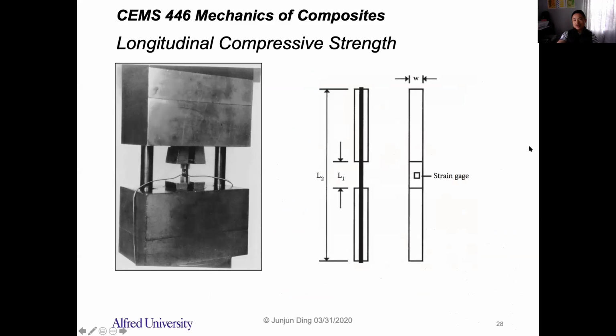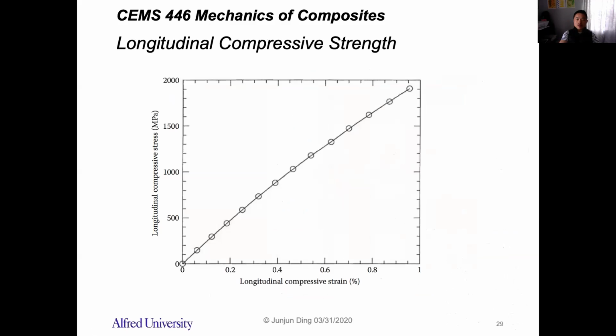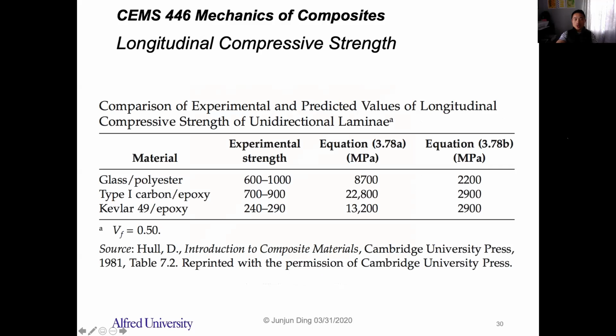You can also measure this compressive strength experimentally. So this is a typical longitudinal compressive stress versus strain curve. It's pretty much a linear curve before failure. This is some examples for the experimental strengths compared with these equations calculated based on the models that we developed. So you see there's a big difference between the experimental strength and this model predicted strength. Usually the experimental strength is much less than the theoretical strength, right? Because the composite is not perfect, right?